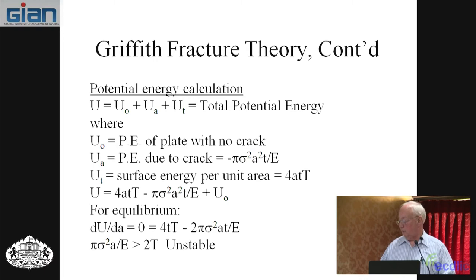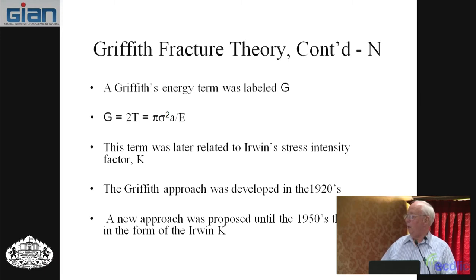So that's unstable equilibrium. Now, that was the Griffiths approach, and he said this is what you need to cause fracture. It's a little bit clumsy. The people who work with Griffiths, and it's still a valuable thing, especially when you have materials that are not homogeneous and isotropic. Nevertheless, the Griffiths G was labeled like this, and later George Irwin came along and showed how this was related to crack tip stress intensity factors. So the Griffiths approach came in 1920s. The new approach from Irwin came in 1950s, so more than a 30-year gap between those two. And some of those failures I showed you were important in developing that, so that was an important thing.